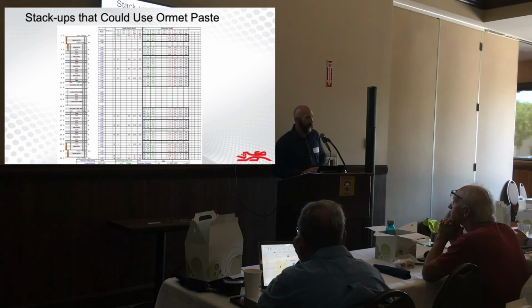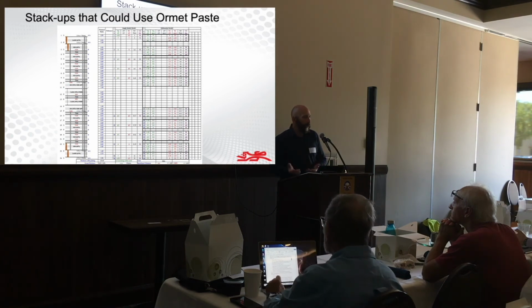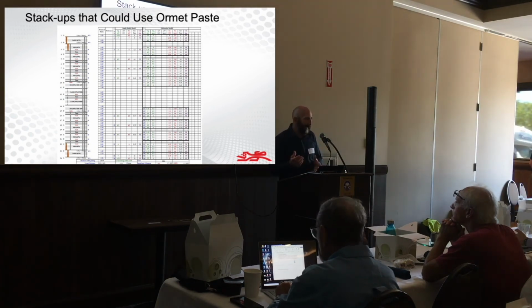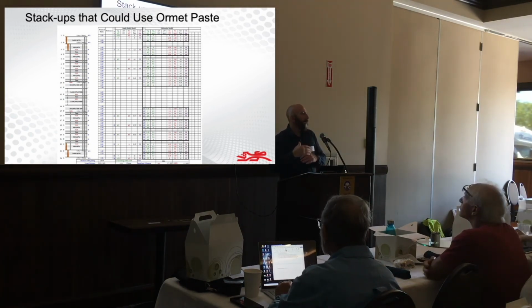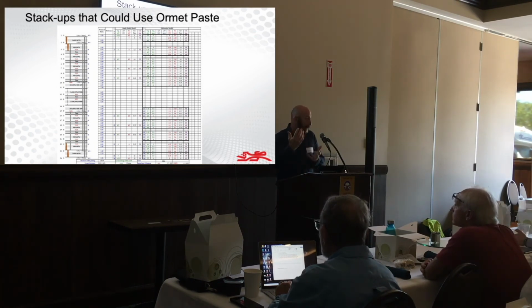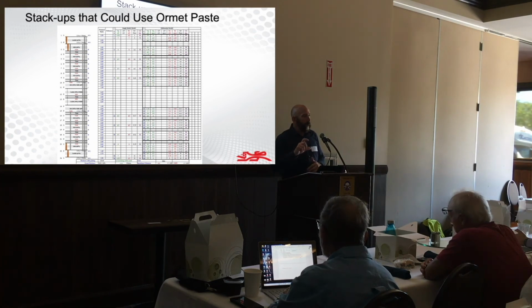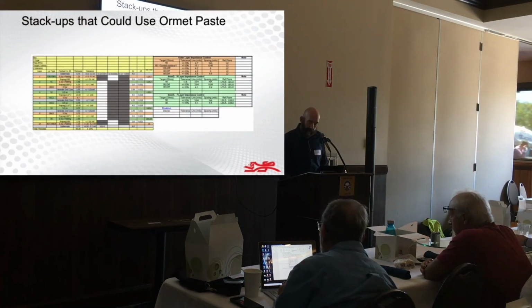And here's the other key point: sometimes I've seen designers and fabricators forget their rules when it comes to fill of copper circuits. So let's say I have half-ounce circuits. I've electroplated, now I'm 1.5 mils thick, something in the order close to 1 ounce. I wouldn't use 1-ply prepreg to fill 1 ounce circuits, because you need a certain amount of resin. You don't want resin voids; they're pretty bad. So you want to use enough dielectric to fill the circuitry you're bonding together, and then make the via diameter 1:1 or less, so you get good Ormet interconnects.